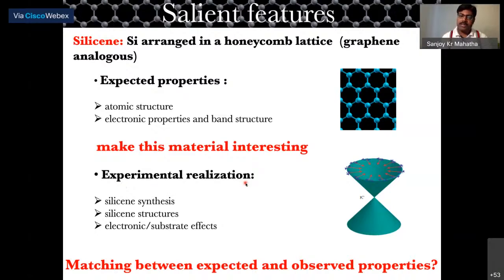the experimental realization of all these is really challenging, because we have to synthesize silicene on top of some substrate, and then there will be some kind of structure which we need to examine, and then there might be some effect from the substrate. I mean, the substrate electrons can hybridize with the silicene electrons and can somehow distort the electronic properties of the silicene. So that's why matching between expected and observed properties would be quite a challenge.